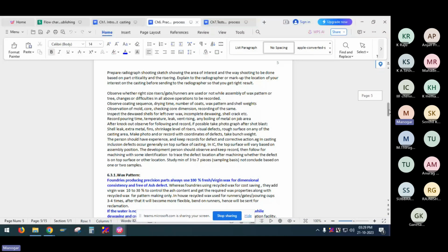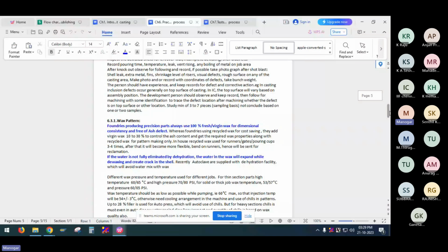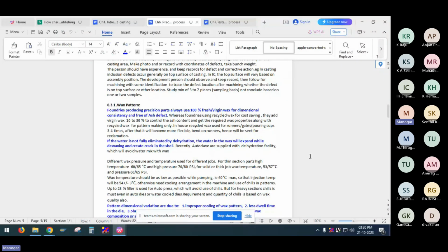And in wax patterns, it is suggested to use 100% fresh wax or virgin wax for dimensional consistency and freedom from ash defects, for high volume and very precision parts where minor defects are not acceptable. Normally, foundries mix recycled wax with the virgin wax simply for cost effectiveness, but for high precision and high volume, virgin wax is advisable.